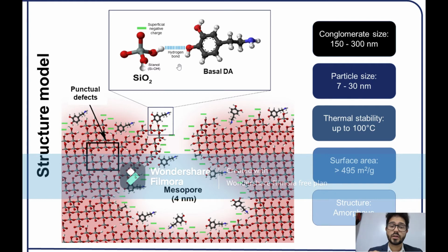Nanoreservoirs are composed of an amorphous silicon dioxide matrix with high presence of hydroxyl groups, silanols, point defects, and a negative surface charge and a high concentration of Lewis-type acid sites in the matrix, in which dopamine is stabilized by the presence of the charges at the molecular junctions. And the presence of mesopores of around 4 nanometers results in high surface areas of about 500 square meters per gram, which translates into the ability to stabilize large drug concentrations. At least right now we have 15%.